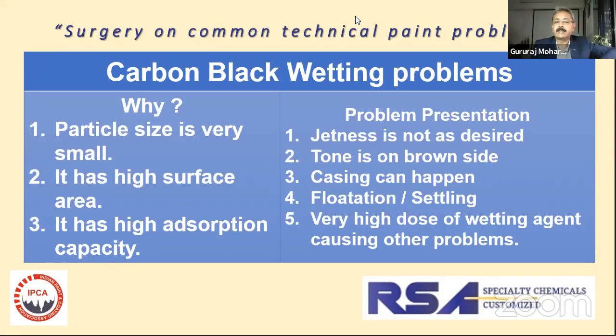The particle size of carbon black is very small. It has a very high surface area. And carbon black also has a very high adsorption capacity. Because of these reasons, carbon black is not very easy to grind. It is a very tedious and painful, very lengthy process. Grinding of carbon black, as I said, ideally happens over 72 hours. So it's not a very convenient thing.